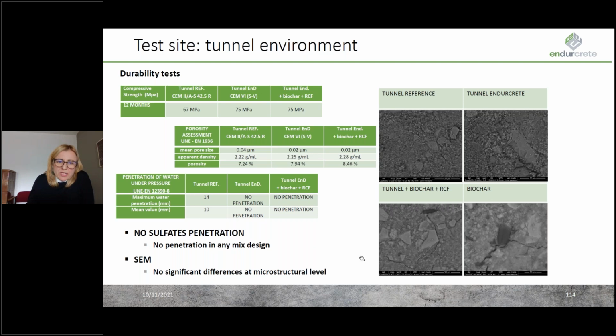No sulfates penetration was found in any of the mixes, and as well the SEM scans showed no significant differences at the microstructure level.